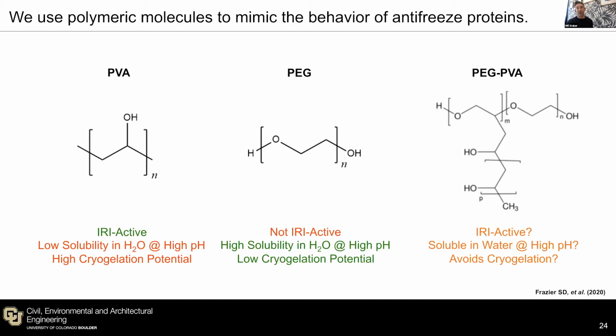So we knew that this couldn't be a viable option to put into concrete. So we turned to biomimicry instead. We looked at polymeric molecules that display the same ice recrystallization inhibition activity as the proteins. And in the literature, we found that polyvinyl alcohol was a polymer that displayed this activity. The issue with polyvinyl alcohol was that it had really low solubility in water at high pH, which would not work out well for us. And it has what is called a high cryogelation potential, meaning that if you freeze and thaw it, it forms a hydrogel and wouldn't behave the same way as it would just dissolved in solution.